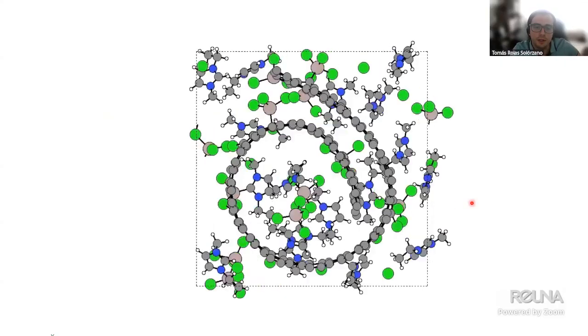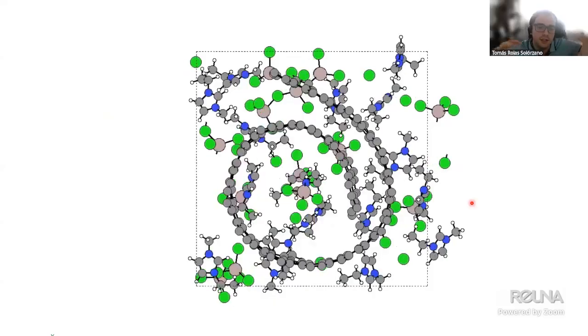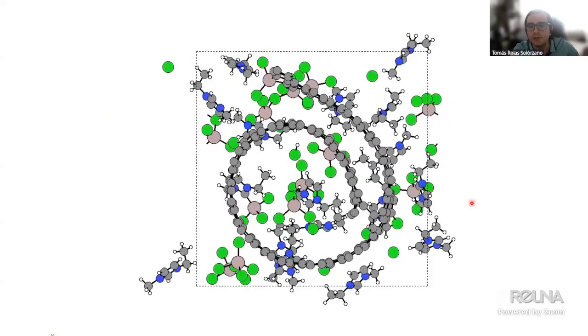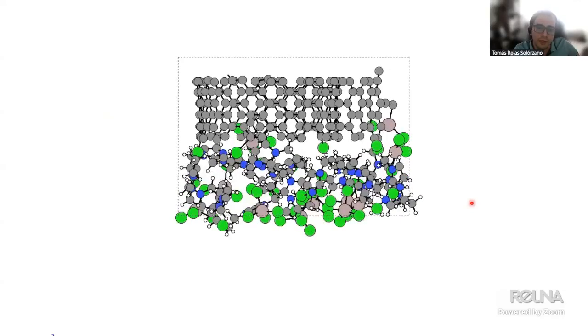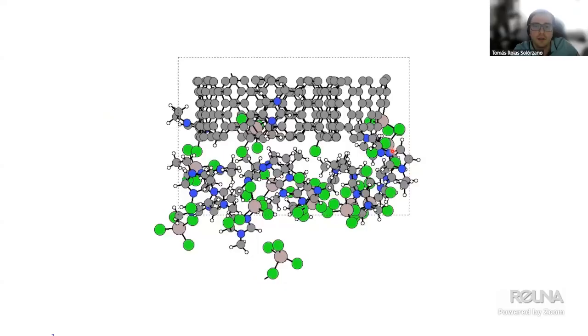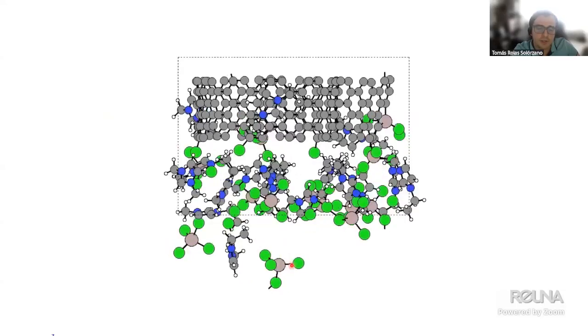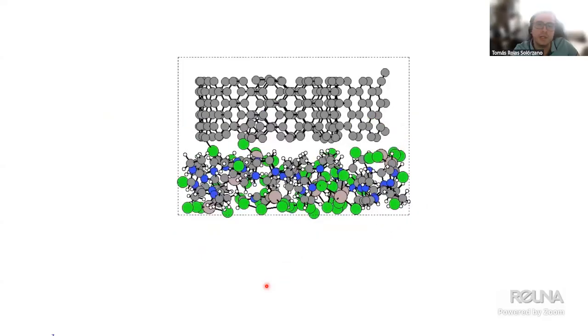is that we can easily see the composition. We will see easily in the other scale. A few things are very interesting from these results. We can see again the easy formation of chlorine layers there, also aluminum there. But this point here is plotted in this part, but it relates to the next image, because these calculations are with periodic boundary conditions. It allows us, but I cannot go back now, to picture the easy formation of AlCl3 to AlCl4, and the AlCl4 molecule easily going on its own without any external electromagnetic potential inside the nanoscroll.